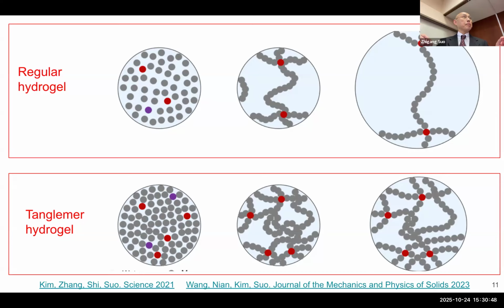And he came because he wished for more entanglements. He said, here's my opportunity. All I need to do is the following. Oh, there's a last step. Because after you make hydrogel, right? The hydrogel is typically used in the body, in contact with water. That hydrogel needs to be stable in water. So the way you make it stable, just put it in pure water, let water swell this hydrogel, and you form a stable network. That's the end product. So that's why hydrogel has a lot of water in it, 90% typical.